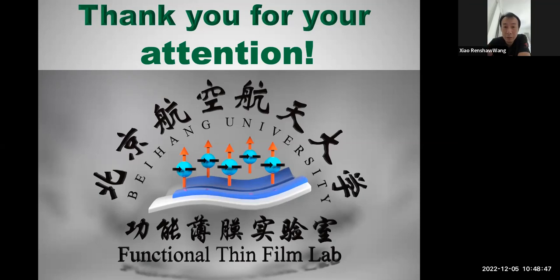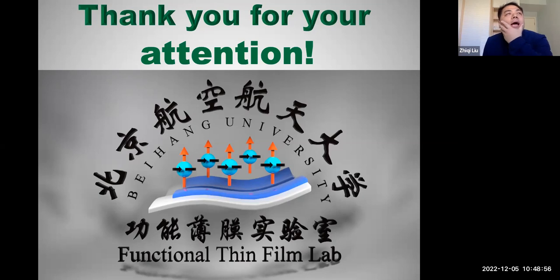So how did you solve the problem? And also, I think in the field, they also can grow 5 nanometer, 2.5 nanometers. How did they solve the problem? So actually, we had similar issues. For ferroelectric oxide substrates, their surfaces are not perfect because of the ferroelectric domains.